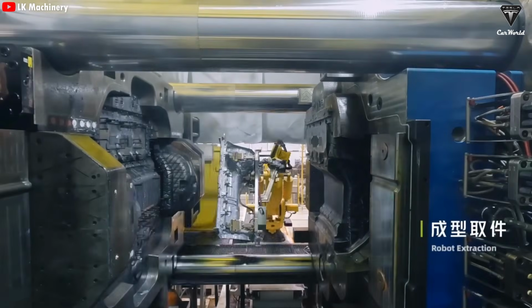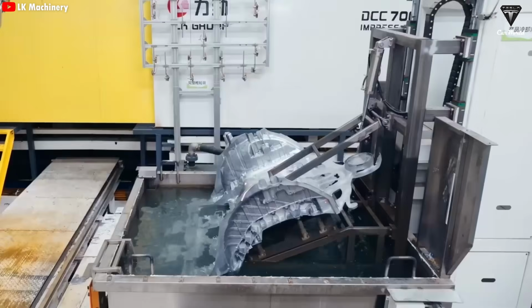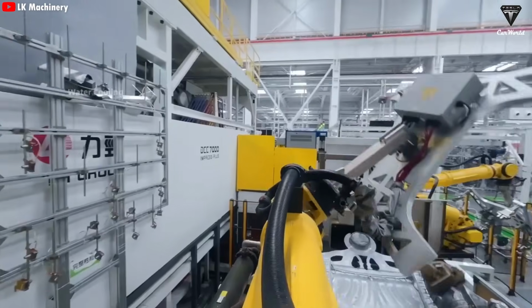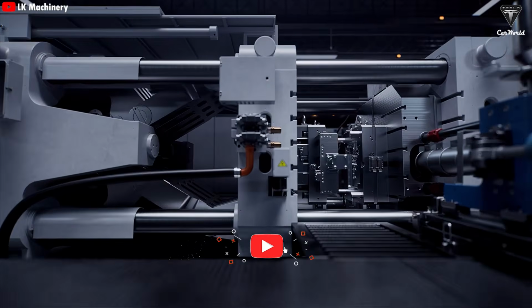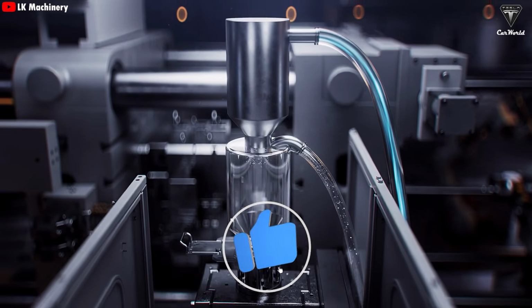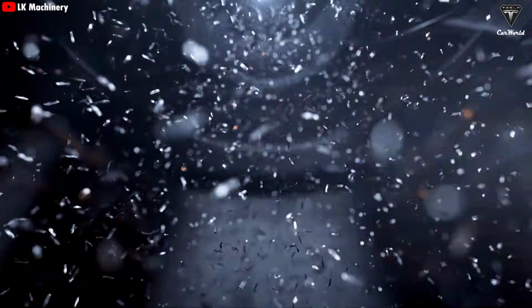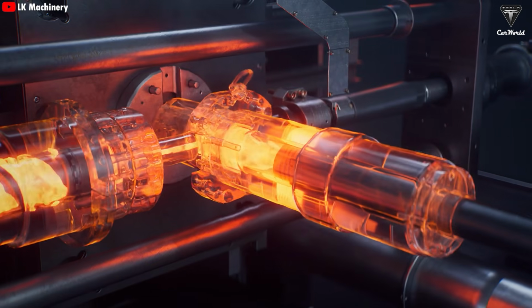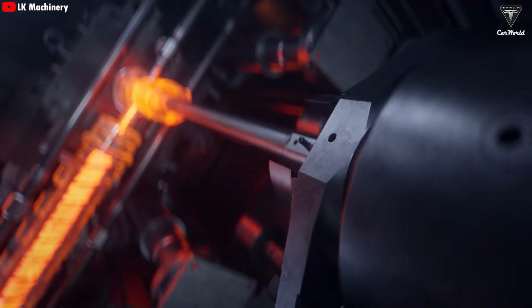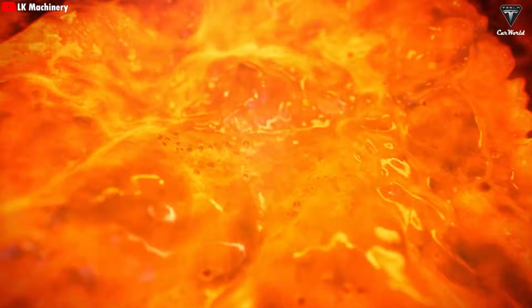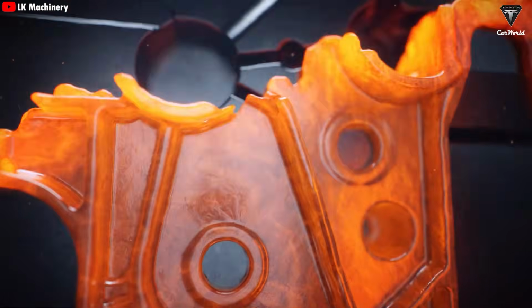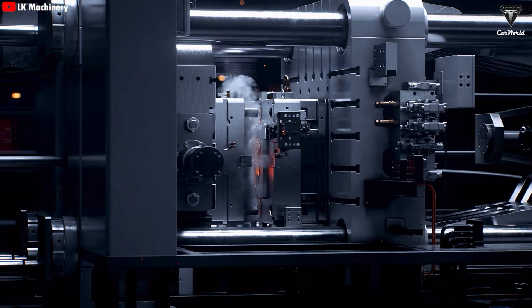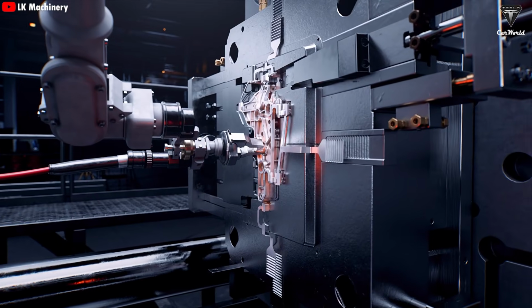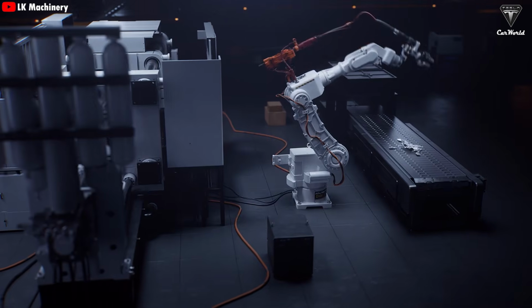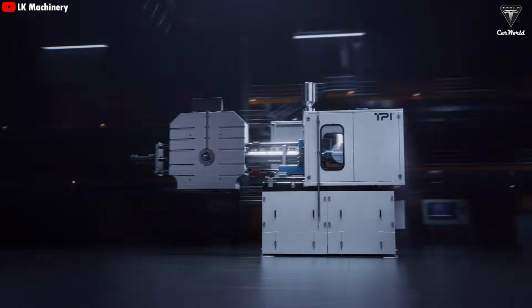The molding process of the 50,000-ton press used by Tesla is also more advanced than that of standard casting machines. We'd even say it's more complex. Understandably, with more molds, the aluminum metal has to travel farther, which increases the chances of defects. If the injection is too fast, air bubbles can form in the metal, compromising the structural integrity. But if it's too slow, the metal may start to cool before fully filling the mold, resulting in incomplete or uneven parts. That's why the casting system of the 50,000-ton Giga Press must operate with extreme precision, down to the exact second, the exact millimeter, or even more.